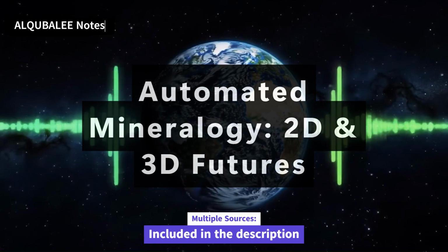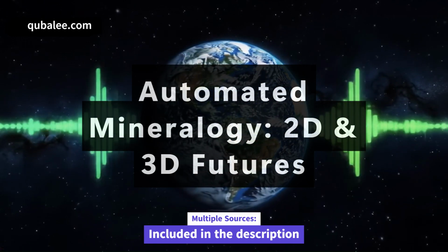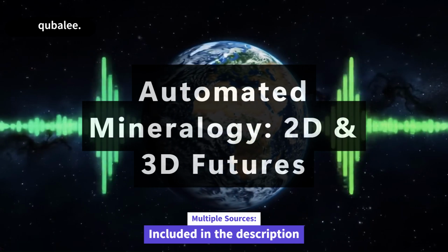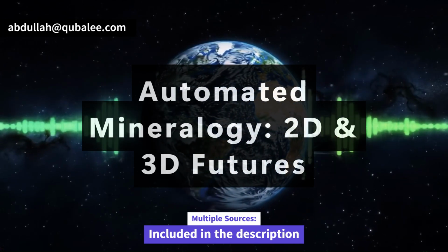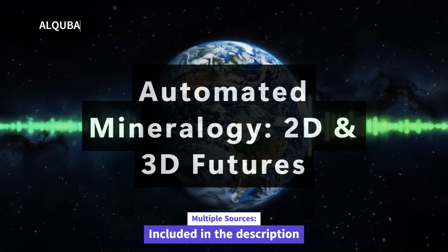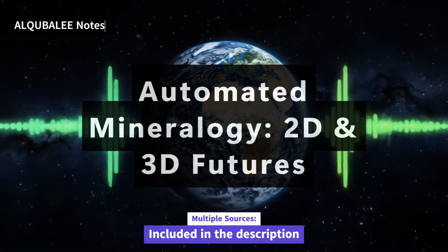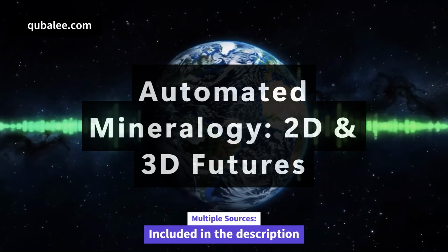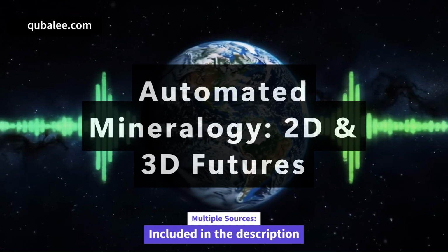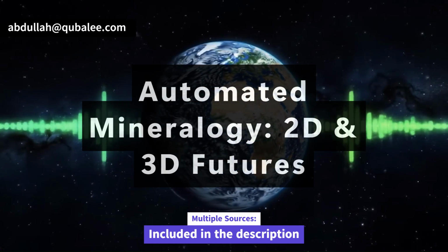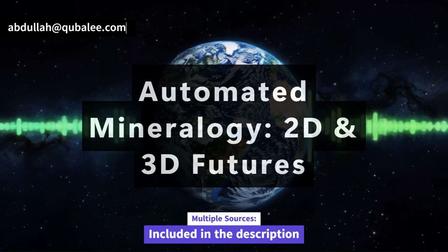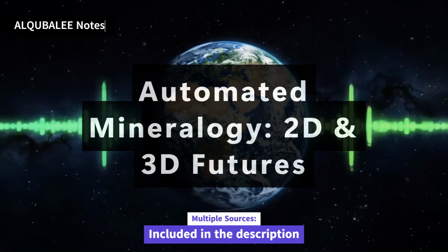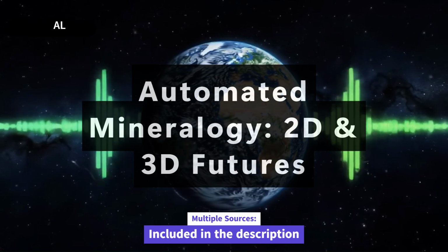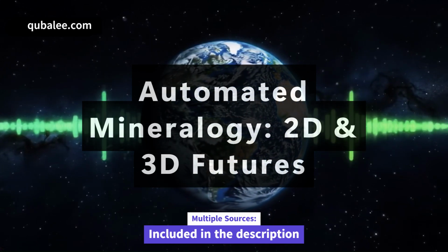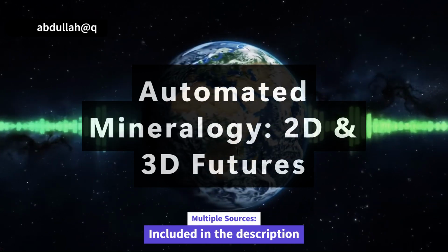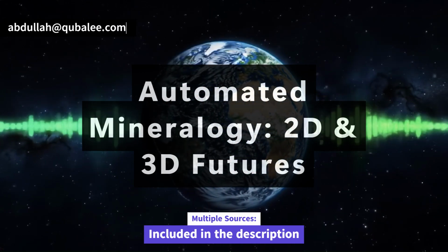Okay, that makes sense for major elements, but I remember reading something really cool about detecting elements present in really tiny amounts, like impurities. Yes, exactly. For elements that are only there at very low concentrations, maybe fractions of a percent, trace impurities like the example they gave of cobalt in pyrite. Right, the cobalt example. You can tell the system, whenever you identify a pixel as pyrite, I want you to dwell longer, acquire counts for a longer time, specifically on that pixel. So you're focusing the analysis time just on the mineral you care about to boost the signal for those trace elements. Precisely. You spend more time collecting X-rays only from the grains of interest. This significantly lowers the detection limit and improves the accuracy for quantifying those low-level elements.